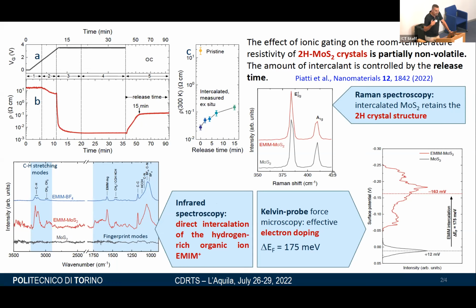You see that it has exactly the same peaks. Does this make any difference in terms of electronics? Yes, of course, because we see that there is a shift in the Fermi level by using Kelvin probe microscopy. All the details are on the poster. We can determine that there is actually an upward shift of the Fermi level by 175 millielectronvolts. So we are actually doping with electrons.